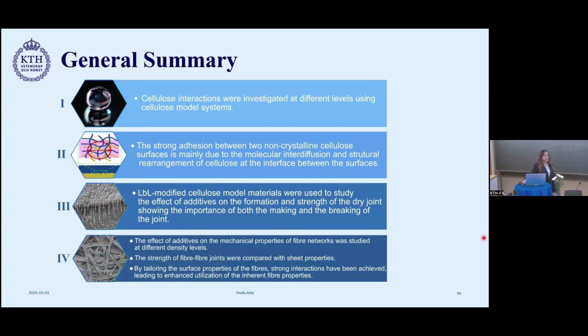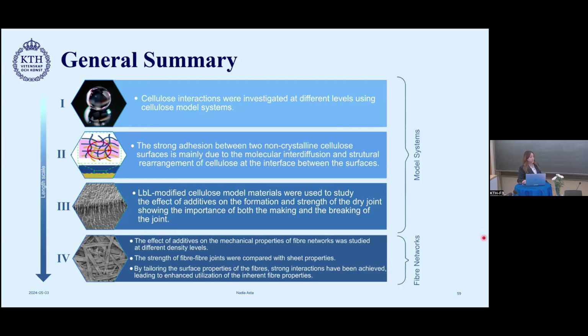And finally, the effect of additives on the mechanical properties of fibrous networks was studied at different density levels. The strength of fiber-fiber joints were compared with sheet properties, and by tailoring the surface properties of the fibers, strong interactions have been achieved, leading to enhanced properties and enhanced utilization of the inherent fiber properties. And so with this, we have studied cellulose interactions at different length scales, using model systems all the way to fiber networks.